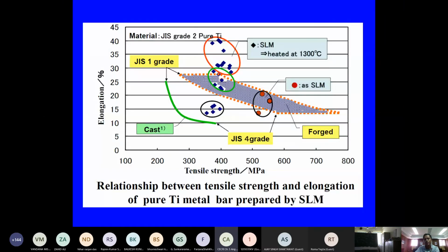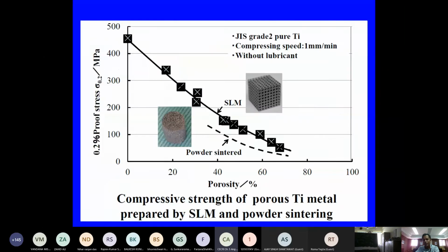And this is another example where we compare where we stand when making the 3D printed component or structure, compared to any of the conventional technologies of casting or forged titanium or titanium alloys. And in this other slide, we make the porous component and measure the compressive strength compared to the conventional method, and we found that in most cases 3D printed or laser melted porous metallic implants or metallic structures have superior mechanical property compared to any of the conventional methods.